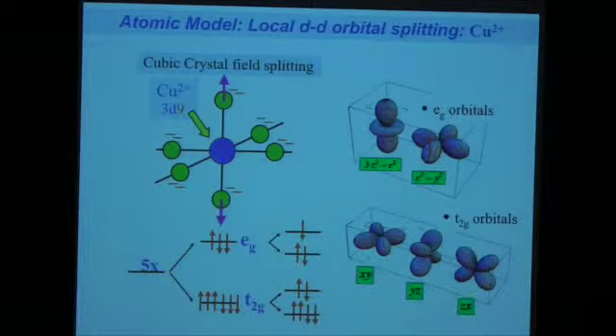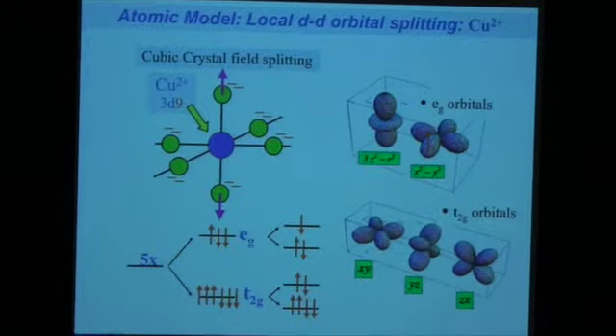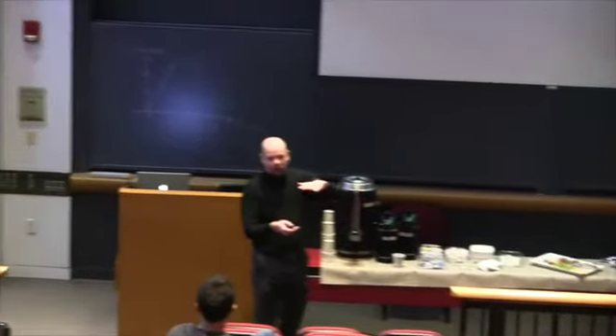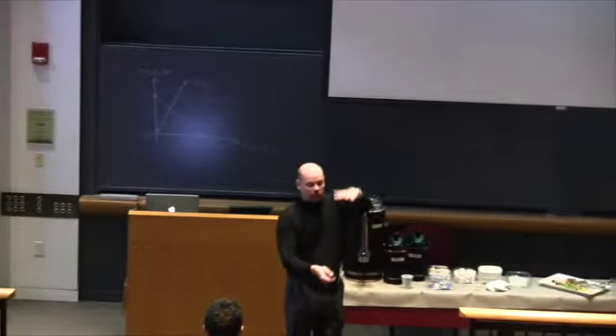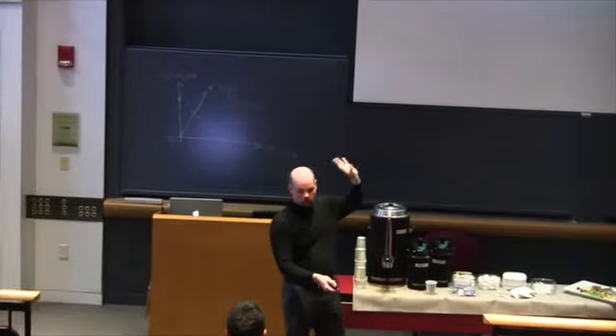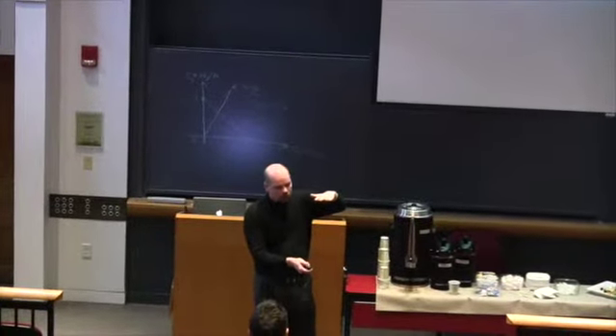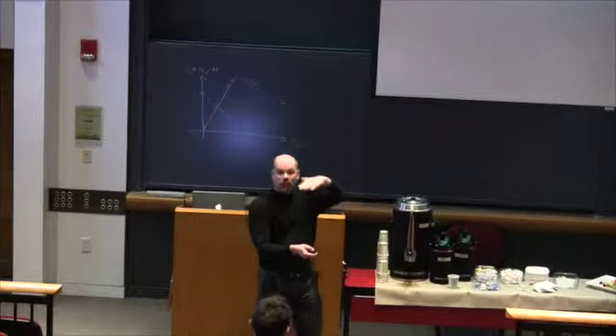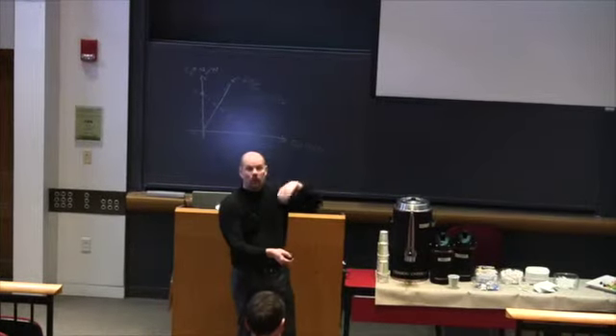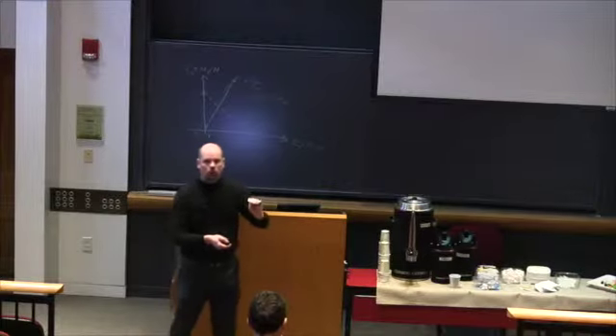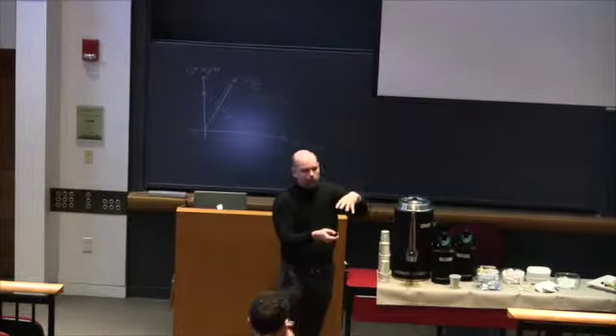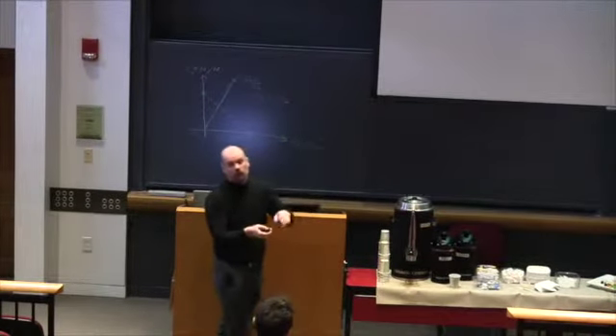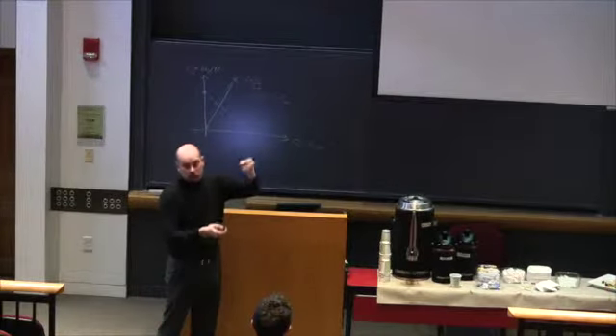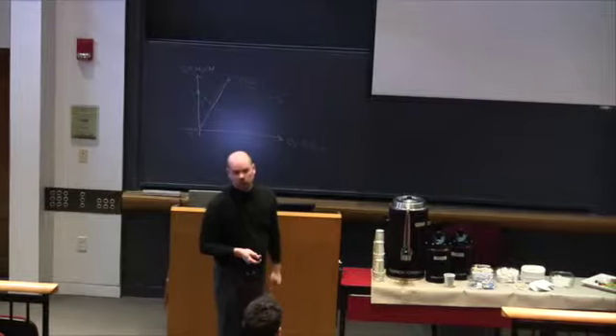So this local, say, quantum chemistry of these orbitals is really intricate. But the splitting of EG, that's just because from Q to Q it's elongated. So why is it much more complicated? I mean, if I have a cubic system and it becomes tetragonal, I know that this is splitting between that I've shown. But we are in a cuprate, and it's not a cubic system to start with. I have my lanthanum oxide layers here, above and below, and these cause long-range Madelung-like potentials on the local copper site. So even if I have a perfectly cubic octahedron locally, the longer range potentials split up already the EGs, and also will split up the T2Gs.